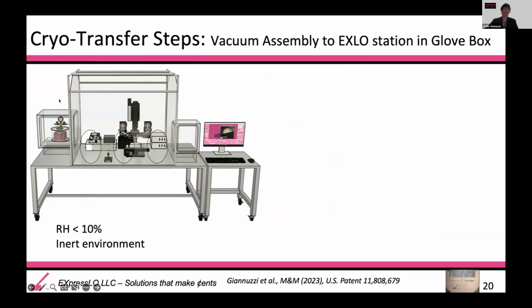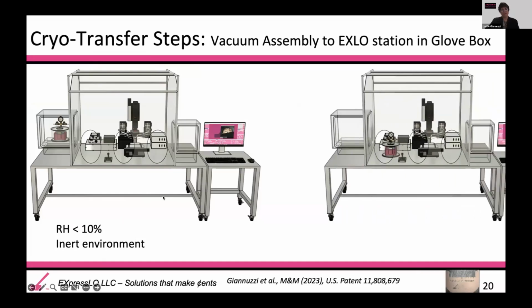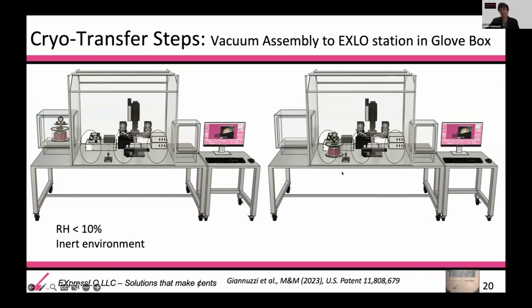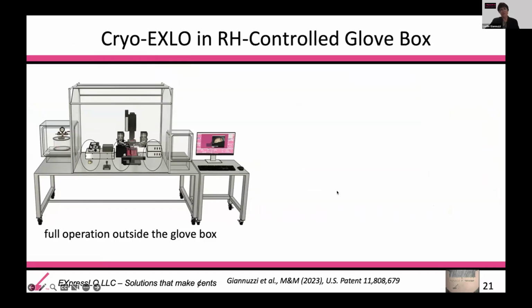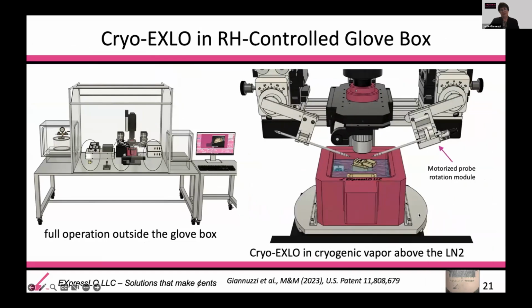We then carry it into our glove box load lock area. The glove box itself can be backfilled, and typically we backfill it with nitrogen. It could also be backfilled with argon. It needs to be less than 10% relative humidity. And then once inside, we disassemble it. We can put it then onto the lift out station, and we can basically start the lift out process.